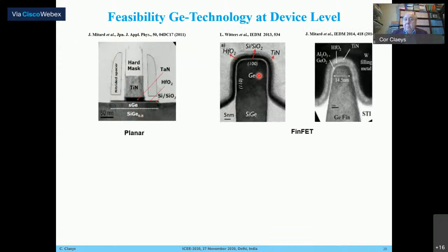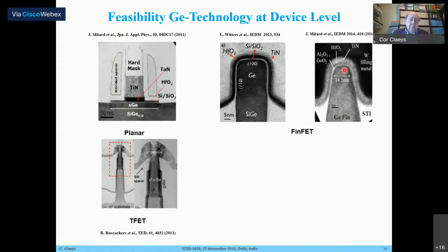You can also use germanium to build FinFETs. Here, for instance, you see a germanium FinFET where, again, the germanium was grown on a silicon germanium buffer layer. But it's also feasible if you optimize your epitaxial processes to grow the germanium directly on the silicon, so that your defects are confined to the interface and in the fin itself you have an extreme low defect density.